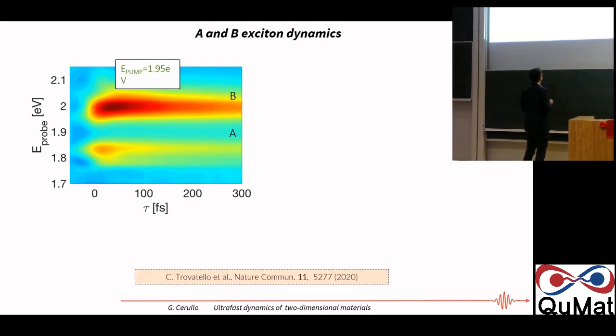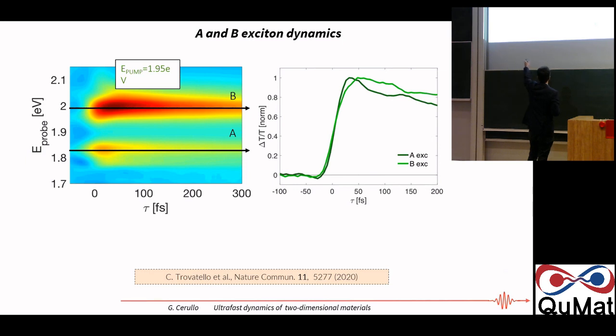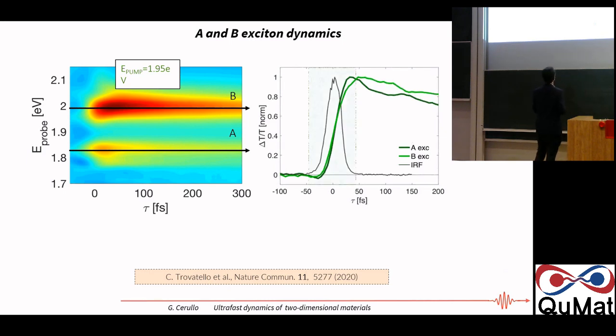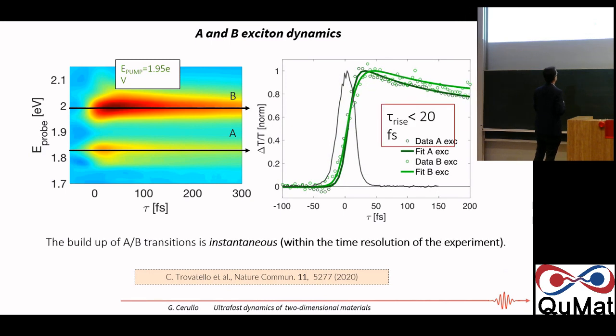Now, if we start with a pump in resonance with the exciton, so it is 1.95 eV, in resonance with the A and B excitons, we see that the signal rises, here you see as a function of time, almost instantaneously, within, let's say, 20 femtoseconds, which is about the duration, our temporal resolution. So we can say that if we pump the excitons on resonance, as expected, the buildup of the excitonic bleaching is instantaneous within the time resolution of the experiment.